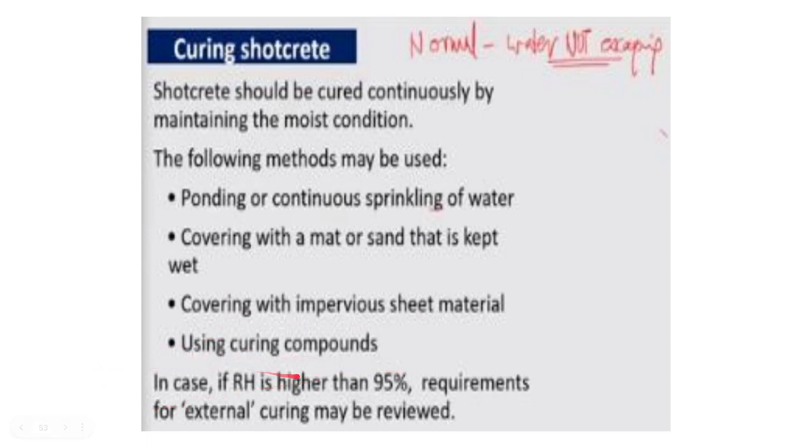Okay, if relative humidity is higher than 95%, then the external curing requirements can be reviewed, because the atmosphere, the environment, has itself a high level of humidity. So in that case, external curing can be relaxed to a certain extent.